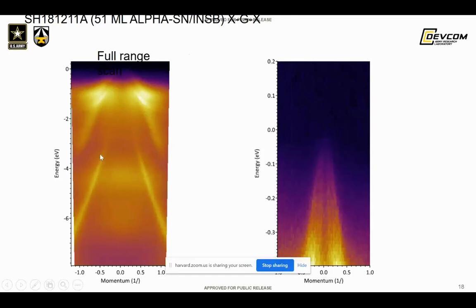This is below the Dirac point, of course, but we can see evidence of some gamma-8 band data that shows up here on the sides. But basically, we see the lower half of a Dirac cone, which is shown up here. It's not that great, but it shows that we're seeing some evidence of Dirac cone formation, as well as evidence of all these complicated band hybridizations with the gamma-8 band shows up in this data.